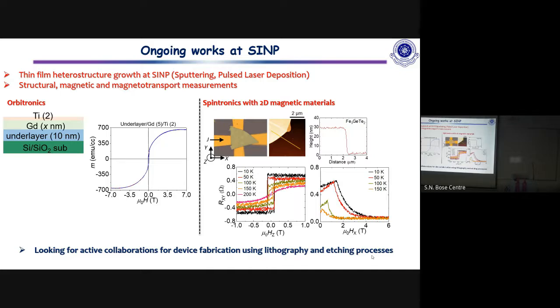So we were able to get very good signatures of anomalous Hall effect from the systems, and we saw that even down to this 30 nanometer, where theoretically it is predicted to be a single domain, in our case, we were still getting signatures of the existence of this spin texture. And this is something which is very interesting. We don't know at this stage why we are getting this, but we are in discussion with some of our theorists who have told us that it could be something different, may not be fermions but something else. So these are the kind of works that I have started at SINP.